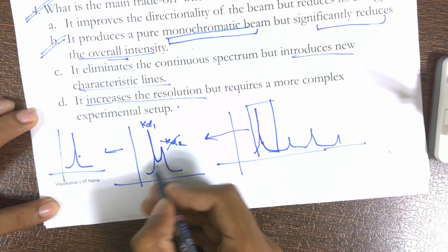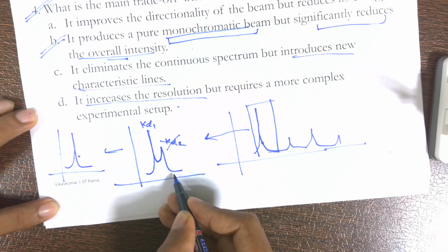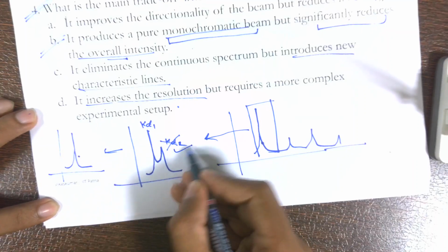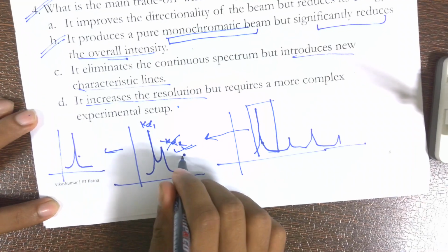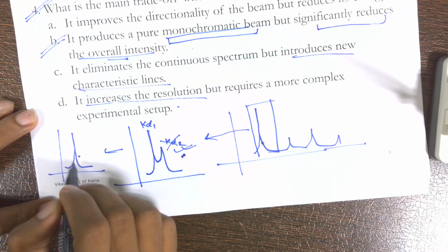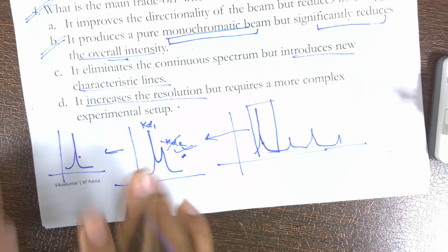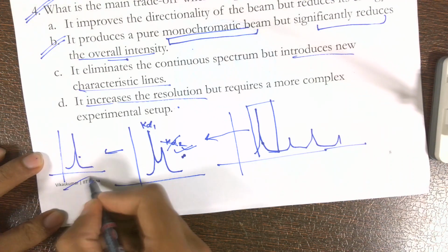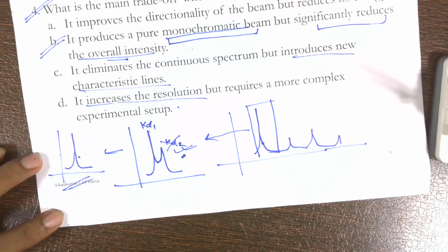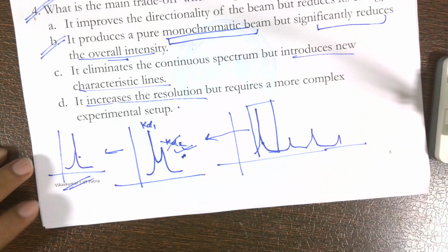Mathematically it will try to eliminate this K alpha 2, which is experimentally not possible to remove. You can just mathematically operate on how the K alpha 1 peak is, based upon the available mathematical models. It usually takes a mixture of Gaussian and pseudo-Voigt functions. So this is what it is from the stripping K alpha perspective.